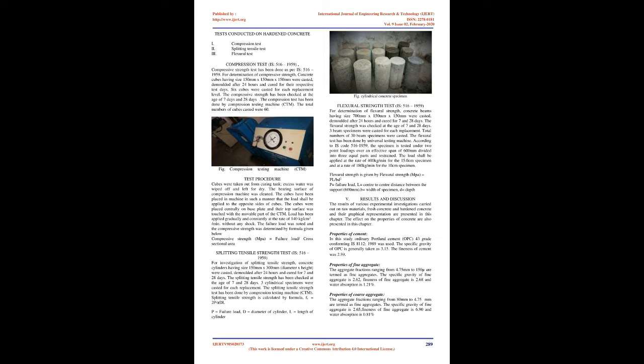It was found that 10% replacement of sand by crusher dust along with 20% replacement of ordinary Portland cement by fly ash gives satisfactory results. It was observed that the concrete containing fly ash, marble powder, and crusher dust was more economical than normal concrete.